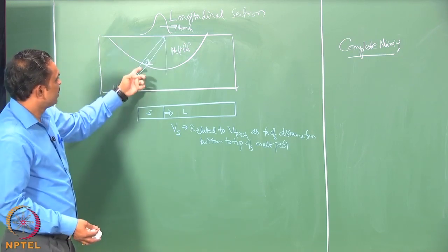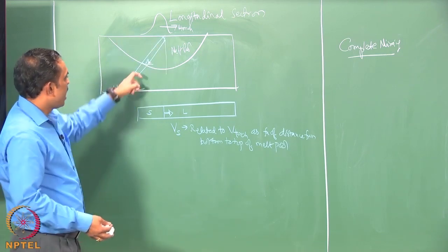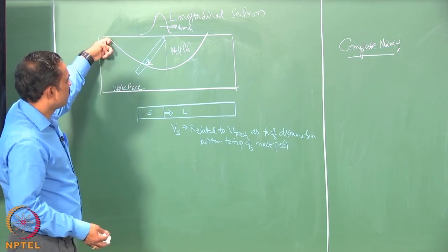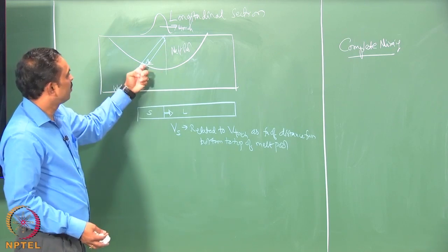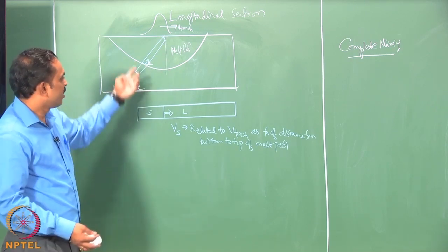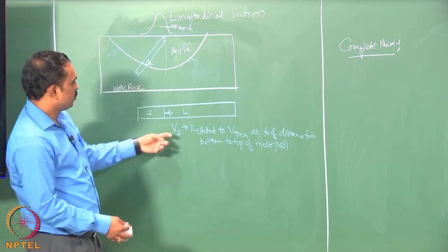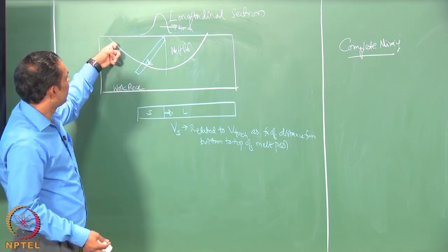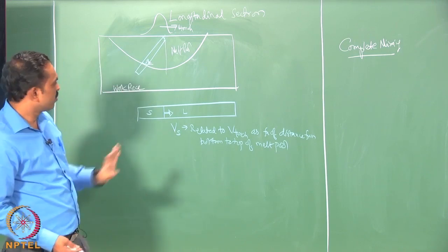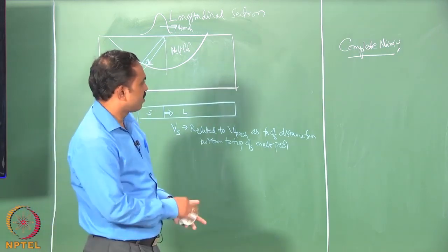It is actually the velocity with which solidification is happening, and you can see that very close to the top it will approach the torch velocity, but at the bottom it is 0. So, somewhere in between it will take a trigonometric function like cos theta to change from 0 to 1, and you could actually determine it at any location using this angle. Okay. So, we will keep that in mind when we need that value.